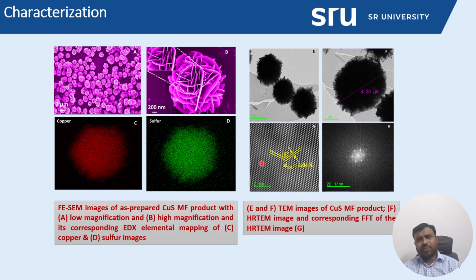So it is observed the copper sulfide has a high crystallinity nature. See here, we formed a good crystal-like morphology. The clear SAD pattern, the bright dots indicate the as-prepared copper sulfide has good crystallinity, and it has strong XRD peaks. We confirm the obtained d-spacing values perfectly match our obtained XRD result.